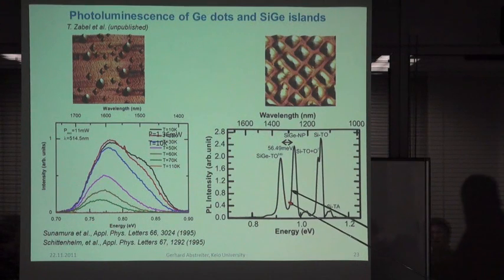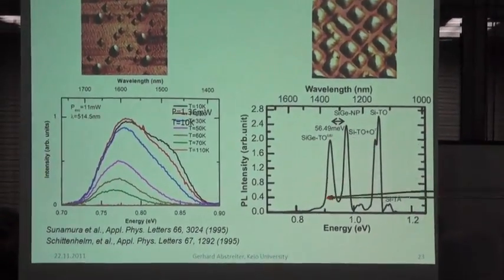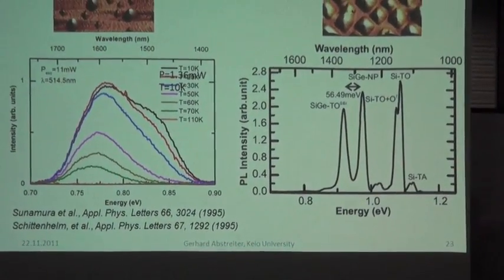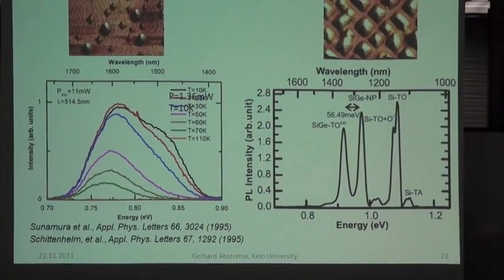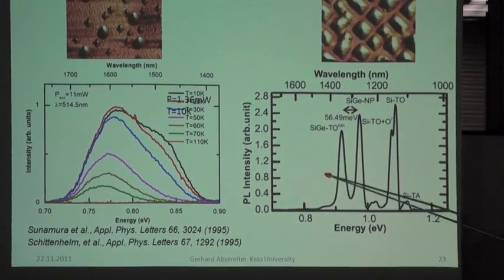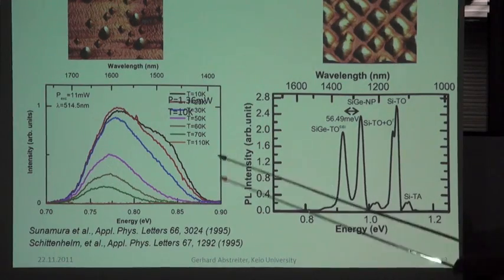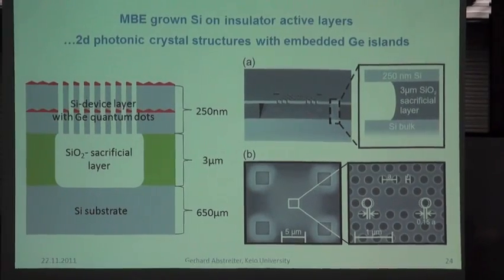And this is the luminescence of these large islands. So this is very new now. And here you see much nicer, like the silicon, the TO no-phonon line and a TO replica, for those who are familiar with silicon luminescence. And we believe that these lines may be better usable than these lines for photonic crystals.